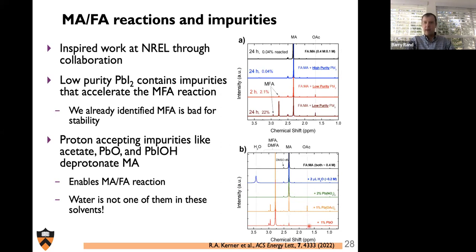byproduct. However, things like lead acetate or lead oxide or systems like this hydroxyl lead impurity will lead to the formation of MFA. And that's because these types of impurities have very proton accepting surfaces and will lead to the deprotonation of MA. And if you create any methylamine in the presence of formamidinium, you will make MFA as a byproduct.